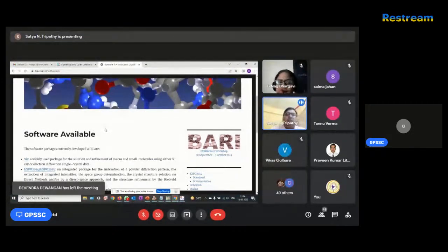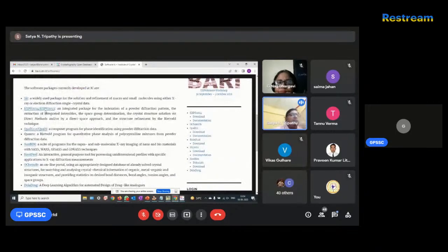We calculate precisely our 2 theta values as well as intensity values. This is very important. You have to collect your XRD data in a very careful way. You run your data here, and it will give you results based on HKL matching, meaning d positions matching. Softwares available within Expo are Treor, DICVOL, and McMaille. These are the 3 softwares available. They will match your 2 theta values and intensity values to a particular crystal structure. They will give you a possible crystal structure. That is the first step.